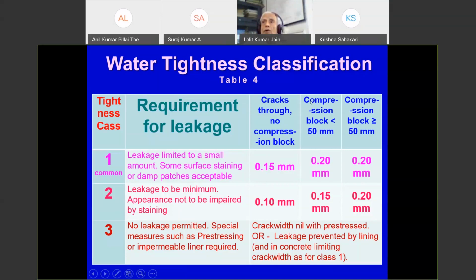But if there is no compression block at all, say when a cylindrical wall is in hoop tension, the crack is throughout and there is no compression block, then the crack width limitation should go down. So 0.15 mm is the crack width limitation. In the earlier version of the code, we were only looking at 0.2 mm as the limit, but now even for water tightness class 1, 0.15 mm will be the limit when the crack is through, or we can say, no compression block is in the section.